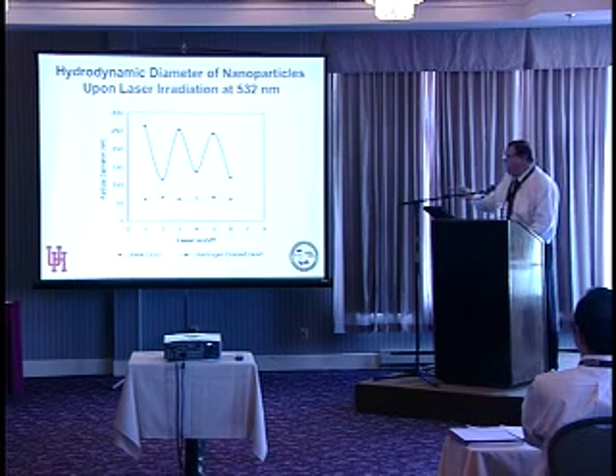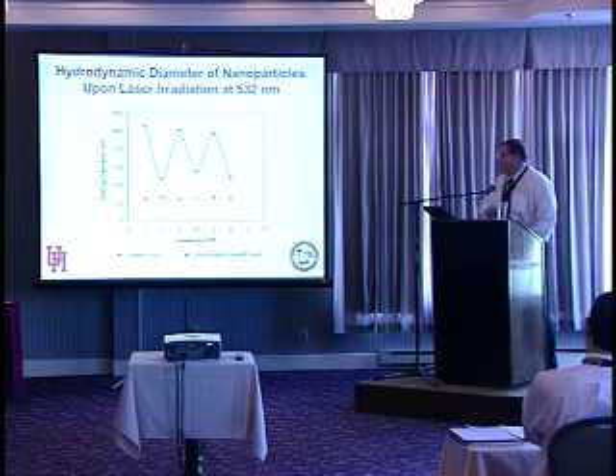again. And importantly, if we use an green laser tuned to about 532 nanometers, since these are just simple gold nanoparticle cores, the bare gold nanoparticles show no variation with laser on and laser off. But if we take the particles, measure the diameter, blast it with the laser, you see the diameter drops precipitously, allow it to cool, measure the diameter again, blast it, and so forth. And we can do this regularly, repeating the collapse and reconstitute behavior of these nanoparticles.